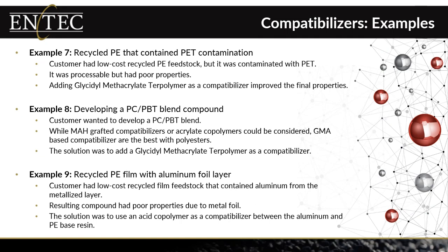And my last couple of examples, recycled polyethylene that contains PET contamination. With a lot of these multi-layer thermoforms and multi-layer film applications out there, there's a lot of different contamination that we can find in polyethylene. We can find PET, we can find polypropylene, we can find nylon, we can find EVOH, and a lot of other things. So in this case, it had PET contamination.